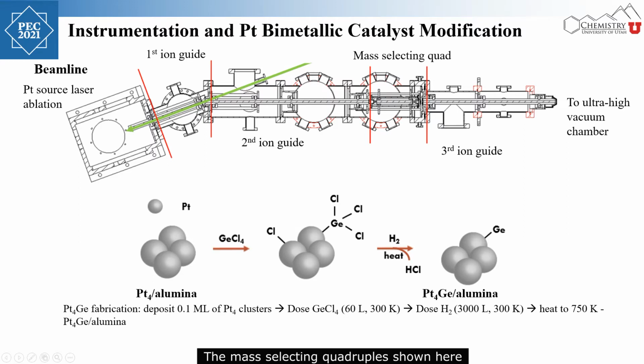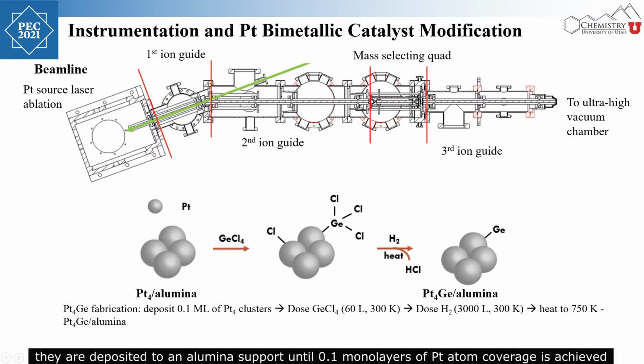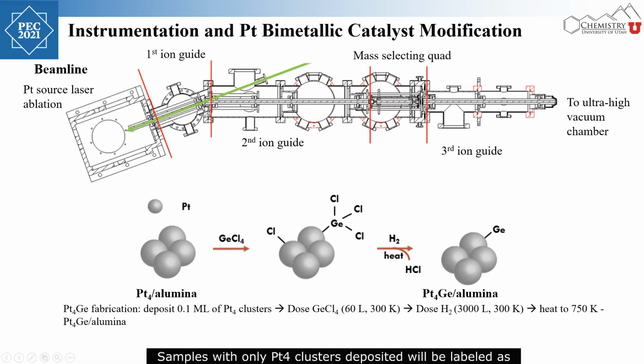The mass-selecting quadrupole shown here specifically selects clusters of 4 platinum atoms, as we found platinum-4 to be highly effective in dehydrogenation reactivity. After platinum-4 clusters pass through the beamline, they are deposited onto an alumina support until 0.1 monolayers of platinum atom coverage is achieved. Samples with only platinum-4 clusters deposited will be labeled as platinum-4 alumina in this presentation.